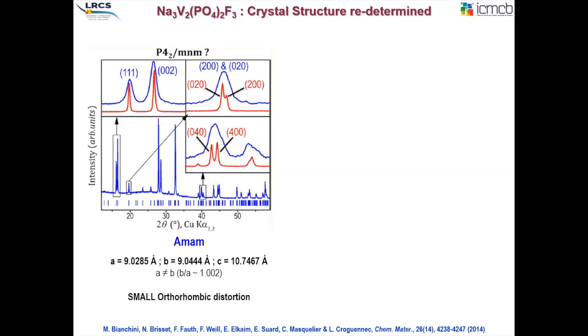First of all, we illustrate here that the compound, when synthesized in the proper way, that means with three fluorine per formula unit, is indeed showing a very, very subtle lattice distortion towards an orthorhombic symmetry that can be clearly seen in red here, where we could identify that what had been previously described in the literature was not completely true. And we indeed proposed this new orthorhombic phase with a very subtle distortion, with, as you can see, a difference of 1.002 in the b over a ratio of this small orthorhombic distortion.